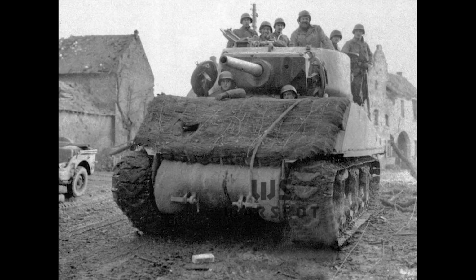The crew bailed out immediately, expecting the worst, but the internal damage was less than they feared. The wet ammunition stowage, a modification that jacketed ammunition in water and glycerin, prevented the catastrophic ammunition fire that had claimed so many earlier Shermans. The tank was disabled, but the crew survived. Even this incident, which represented a jumbo's failure, actually demonstrated the success of American armour engineering. A tank that took 8 hits from an 88mm gun before being penetrated had performed far beyond what any standard Sherman could have achieved. The crew lived because 7 out of 8 hits failed to penetrate armour that, by German standards, shouldn't have been able to stop even one.